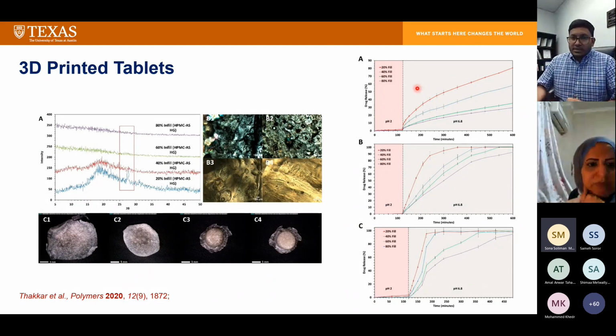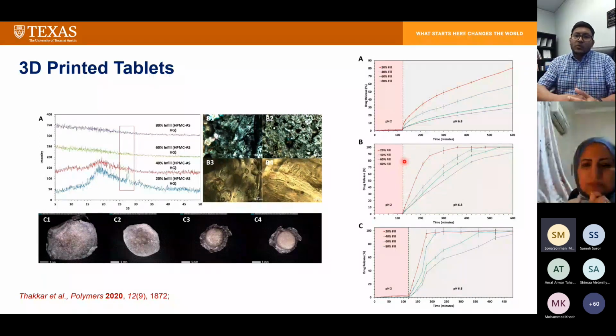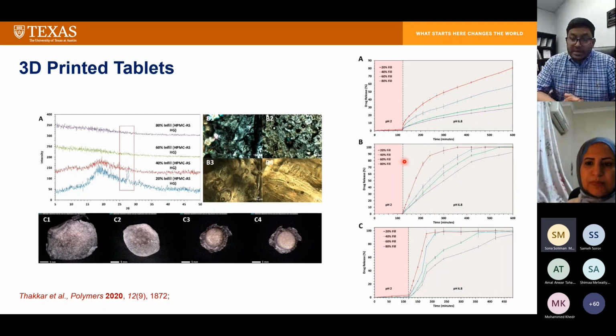Most importantly, when we changed the grade of the polymer, we found that we could also control the release pattern by changing the molecular weight of the main polymer being used in the formulation composition. So this was a really good example case study of using 3D printing where fill density could be used for controlling the release profiles.